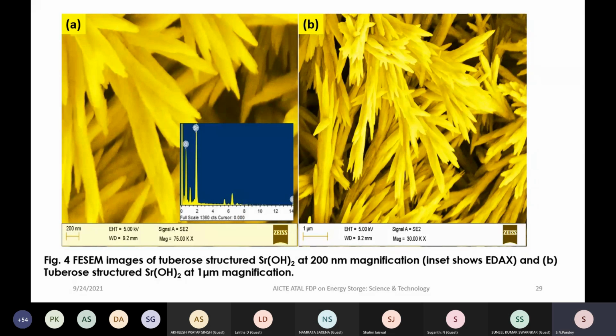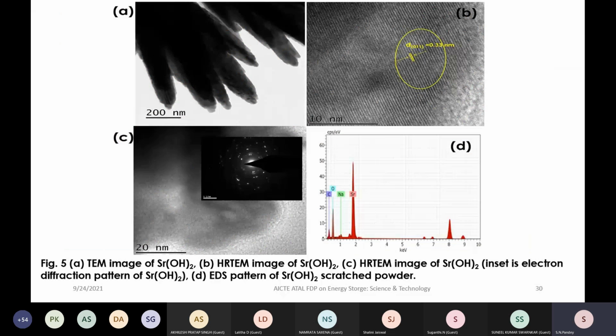So this is the TEM image of the strontium hydroxide. Again, one can see the tuberose structure, and this is the HR-TEM, and the inset is the electron diffraction pattern of this, and this is the EDS pattern of the strontium hydroxide scratch powder. So the scratch powder that we have taken was sent for the STEM characterization, and we are doing it manually. Really, the students have done very hard work, because manually we are completing one cycle,